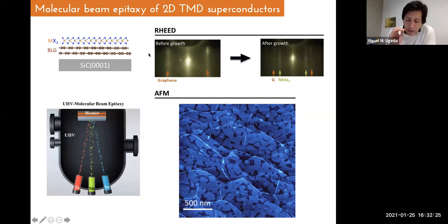In order to monitor the growth of our material in real time, we have a RHEED diffraction pattern that we follow in situ and in real time. So we are able to distinguish where the TMD is growing and more or less to estimate what is the coverage of the material. If it's one monolayer, half a monolayer, two monolayers, etc.